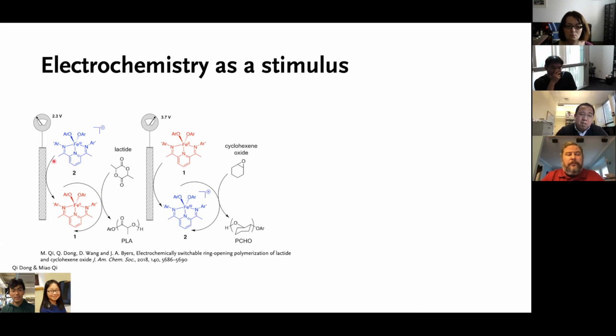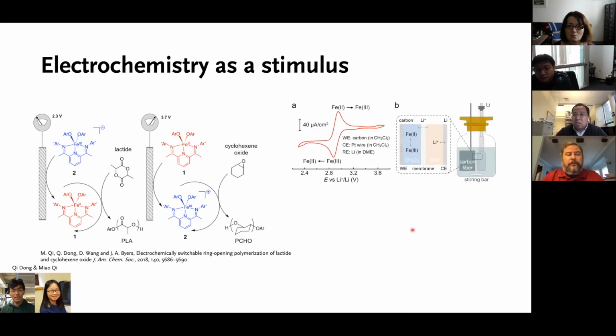But the simplicity is really a little bit misleading, right? So if you apply a reductive potential, you can reduce iron from 3+ to 2+. Alternatively, you can oxidize it back from 2+ to 3+, and hence you can control the different polymerization. Again, the details were presented by Jeff, but I just wanted to mention some thoughts that have gone into the design of the electrochemical cell.